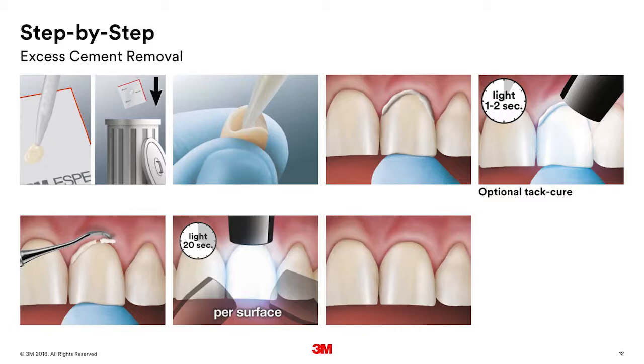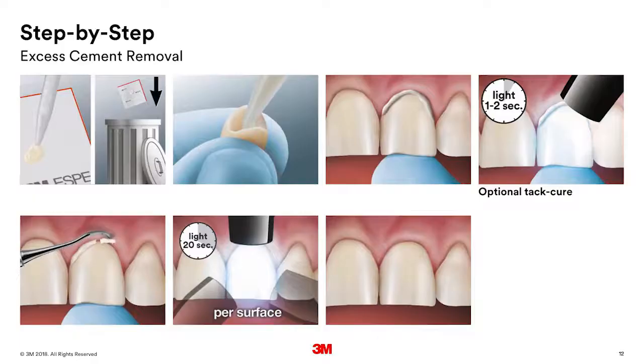Now when I say quick, I mean 1 second, maybe 2, because the cement gets very hard. After you do the tack cure, clean the cement up, and then go back. Once you make sure all the cement is off, go back and then do a more thorough curing of 20 seconds per surface. The way I prefer to do it, just because sometimes lights differ in how much they cure, is put the crown on, have the patient gently bite down on a cotton roll for maybe 90 seconds or so until that cement hits the gel phase. Then it's pretty easy to remove. And again, make sure it's all off before you put that curing light on it. And now do your final cure of 20 seconds per surface.